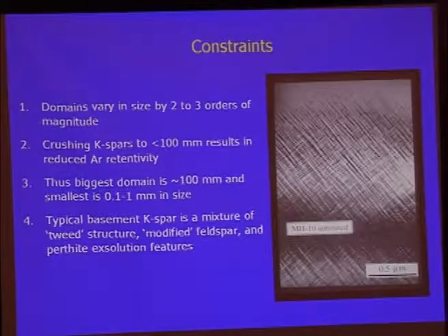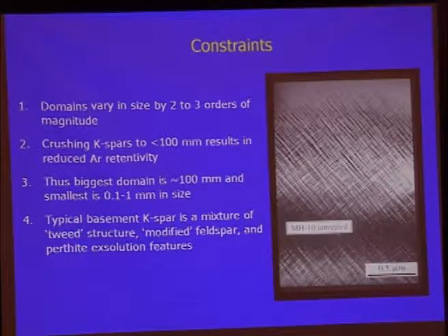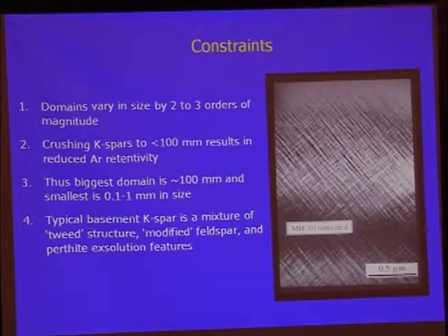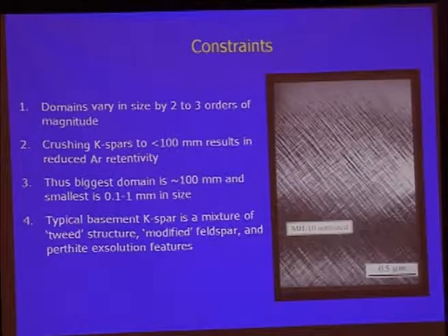This is essentially relatively small variations in triclinicity in this material. If, in fact, at this scale, there were a substantial number of line dislocations, you would be picking it up in a region like this. So this is essentially homogeneous, almost pure orthoclase, varying just by small degrees of difference in triclinicity.